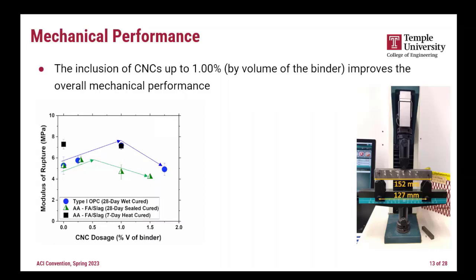Regarding the mechanical performance, by inclusion of the CNC, this is the modulus of rupture versus the CNC dosage. So up to a certain percentage, again, we see an increase in the flexural strength or the MOR of this system by use of the CNC. By using the heat cured for the alkali activated, we see much more improvement, the black dots you are noticing here. The other point is that the reduction at that higher percentage is partly because we are using a higher water binder system. So that's reducing the mechanical performance.